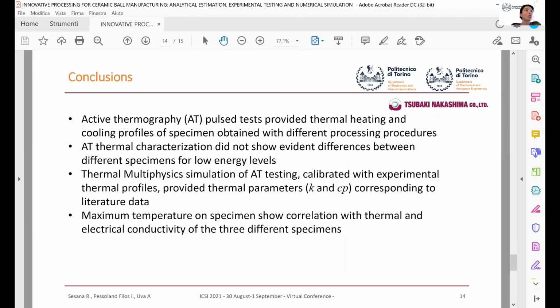Therefore, in conclusion, this work points out the importance of active thermography as a non-destructive technique. In fact, it was possible to provide the thermal transient, both the heating and the cooling down phase, for the 3 different specimens obtained with the 3 different processing techniques. For low energy level, the active thermography characterization did not show evident difference between the samples.